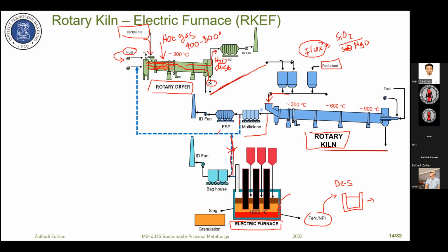If we use the copper cooling, we do not need any flux, except if we have the SiO2 to MgO ratio more than 2.2. In that case, we must add flux. But if you use copper cooling without any flux addition, the SiO2 divided by MgO is roughly around 1.8. We use copper cooling. In that case, the service life of refractory is more than 10 years. In some plants, we have data of more than 20 years.